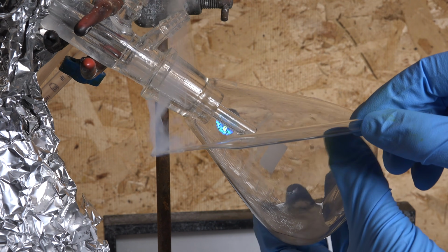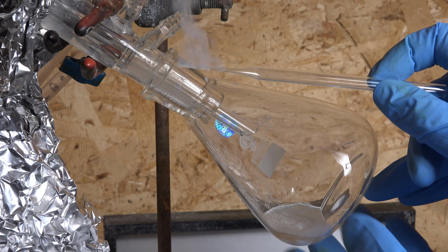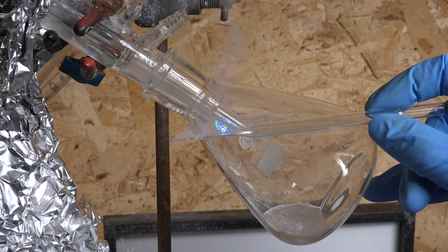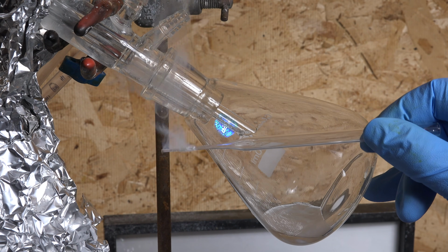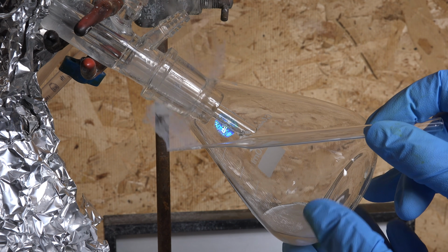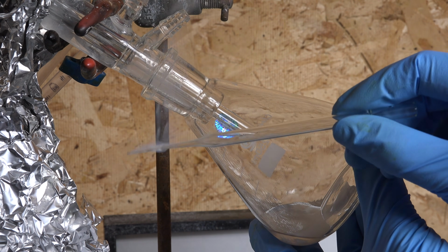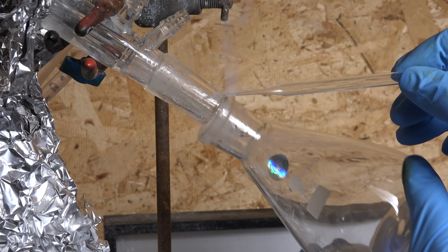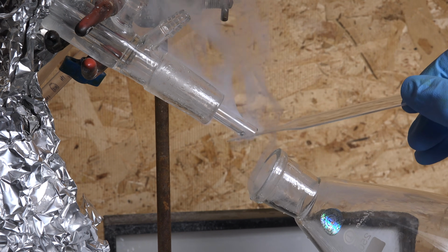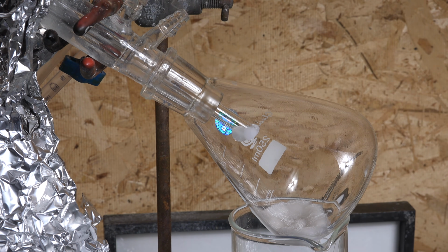Another option might also be the intense fuming of the pipette earlier as a loose indicator that we have the sulfur trioxide. Sulfuric acid does not fume this much, so if we had no fuming, we'd be fairly certain we were no longer distilling sulfur trioxide. The problem is that we have to open the receiver to run the test, and we'd have to do that multiple times during a run. So that's not exactly a good option, but it's something to keep in mind. And it looks like it's getting too big and about to clog again. So I'm going to see if I can melt the clog by turning off the cooling.